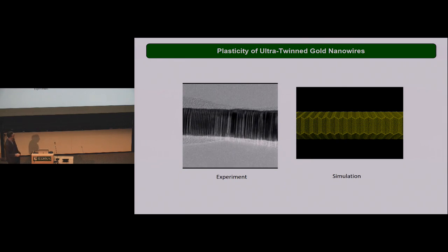So this is the in situ experiment. You see all the twins here playing, and we're not going to see a lot of plasticity here. It's almost a brittle-like behavior. Boom, see here, it just broke in half. But very surprisingly, there's a tip that's formed that does not twin at all.